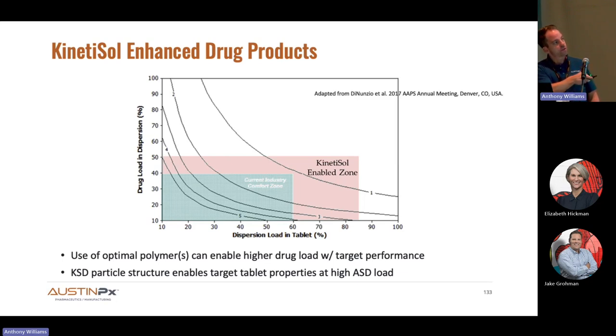So this was sort of the boundary layers for ASD products that were limiting the dose that you could achieve per tablet. And so the part of this that you can't see is with KinetiSol and our ability to utilize a combination of polymers and other excipients, we can often achieve higher drug loads with similar performance. So based on deferasirox and some other examples, I put our boundary layer at about 50%. And then based on our number of case studies, we can get acceptable tablets as high as 85% ASD load in the tablet. So the KinetiSol enabled zone for a typical tablet extends beyond the industry's comfort zone based on melt extrusion and spray drying.